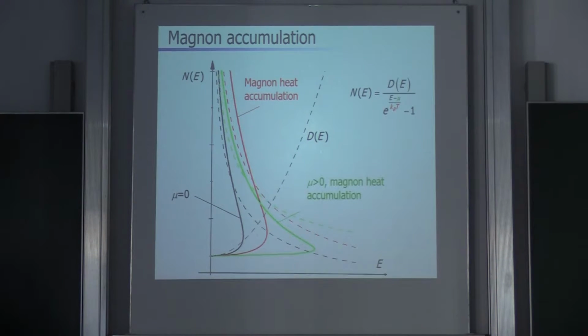Now let's assume that we are exciting our system. So we are exciting a distribution of very hot magnons. So what's going to happen? First of all, we assume that only the magnon-conserving processes are relevant on the fast timescales. So that means that if we have hot magnons on top of cold phonons, right, there will be an energy exchange between the phonons and the magnon system. So the phonons will maybe get a little bit warmer, but the magnons will get colder. Right. So that means we get a distribution function which goes from here to this one here.